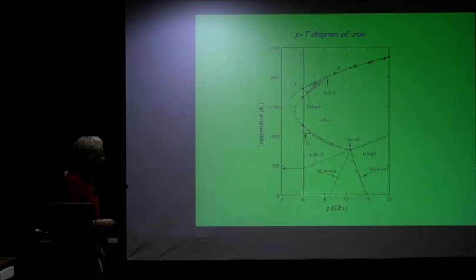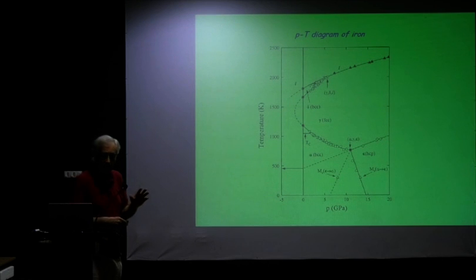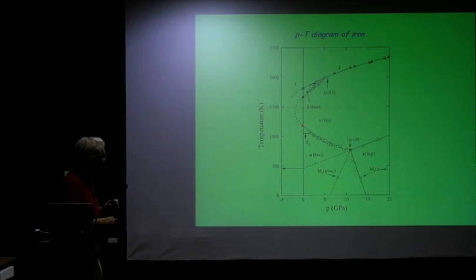So now, when we increase the pressure, what you see here immediately is that the close-packed structure stabilizes to lower temperatures. So this transition temperature here shifts further and further down. And here also, you find that it goes more and more upwards. So this gamma phase region expands when you apply pressure. The gamma stability range, which was this, at certain pressures becomes something like this here.